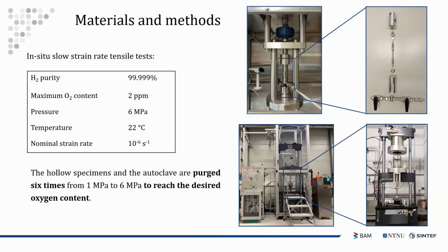And also the tests were conducted at room temperature with the same nominal strain rate of 10 to the minus 6, so very slow strain rate. And in the case of the autoclave, the sensors were able to monitor online the presence of hydrogen, so we can guarantee that the nominal testing conditions were kept constant during the entire duration of the test, which is approximately 3 to 4 days for tests conducted in hydrogen.